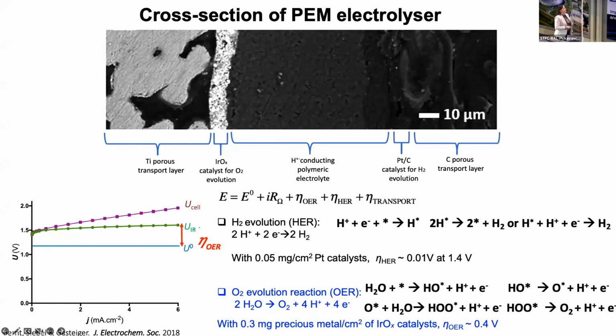Now, if you look at the overall efficiency, we all know that water splitting happens at around 1.23 electron volts. Of course, you have some resistance here, and this is normally the potential of a cell. The potential of the cell is due to the fact that you have quite a lot of overpotentials. For hydrogen evolution, these are the potential steps here. So you see that you have mostly one intermediate, so you don't have so much overpotential here. With only 0.05 milligrams per square centimeter of platinum, you could nicely evolve hydrogen.